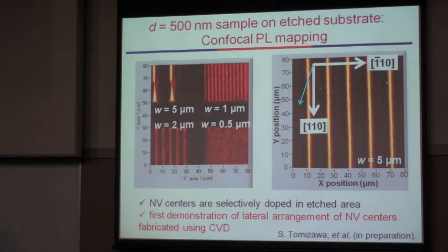So this is a result. As you can see, the NV center can be doped in a specific area, which corresponds to the etched area. So we can demonstrate the spatially selective doping of NV centers by using the nitrogen-doped CVD method on a micro-patterned substrate. This is the first demonstration of lateral arrangement of NV centers fabricated using CVD.